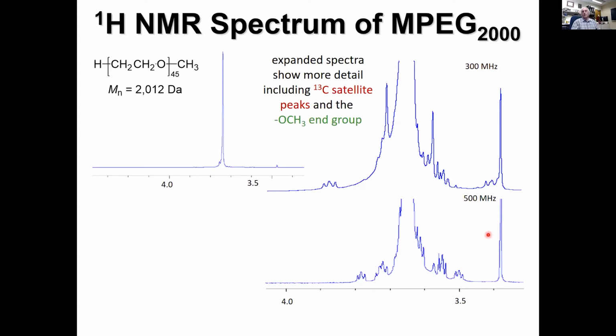If I add a little bit of an internal standard, I could have a small amount that would be an area corresponding to 1 or 3, and I could actually do that integration also very well. The nice part is that this relative to this is always going to be the same. This is always going to be 0.5% of this.